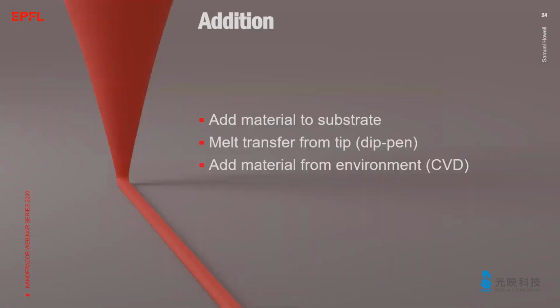So the third modification is addition. So besides removal and conversion, one can also add material with a thermal scanning probe. And one common method used is where a heated tip is loaded with a low melting temperature material, such as a polymer or indium, a metal with a low melting temperature.